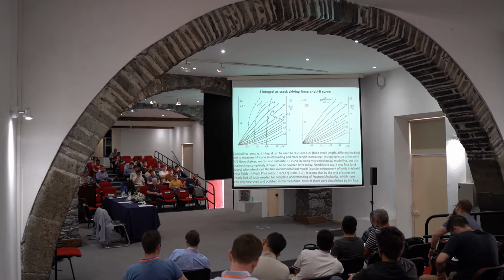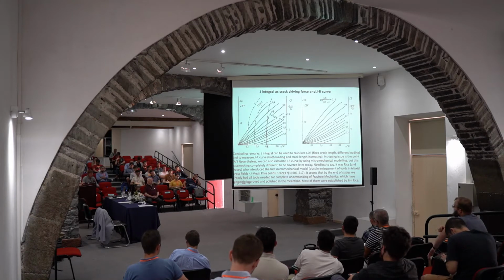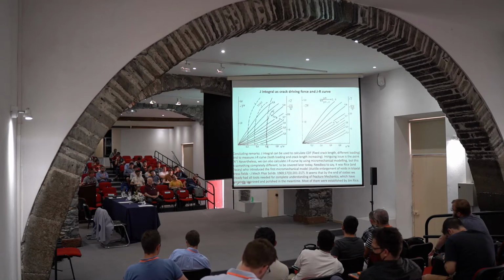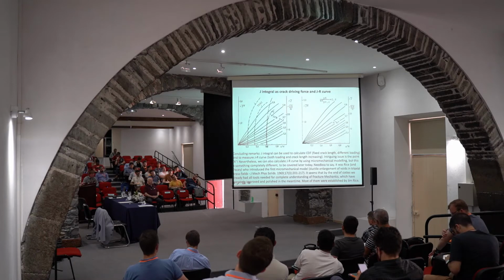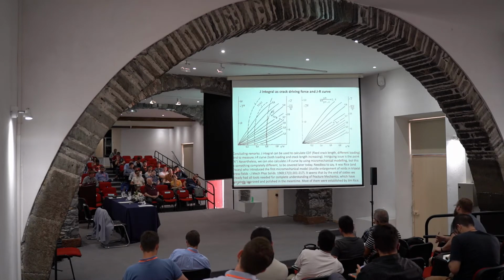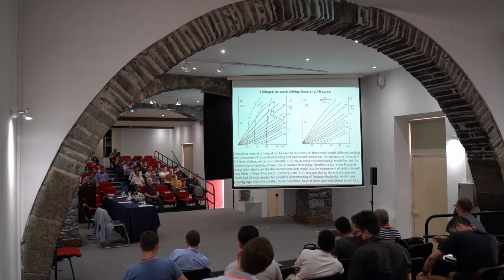You can see them here, positioned at the crack depth, which is 60% of the thickness, or here when it is 35%, or here when it is 20%. We just tested different cases. And at the point where crack driving forces are intersecting with JR curves, we can establish a critical point.